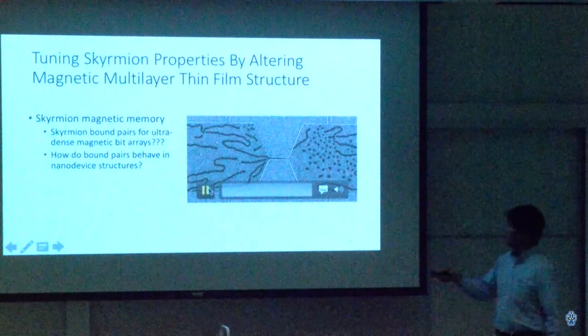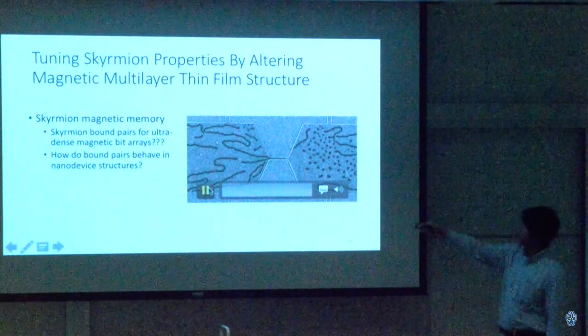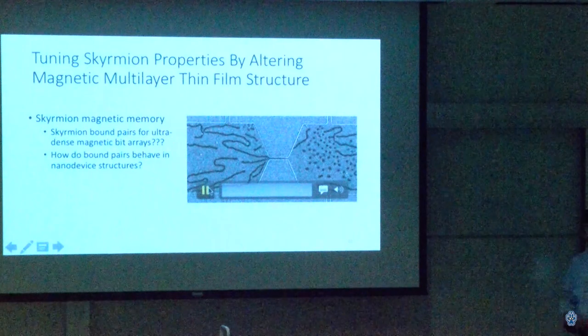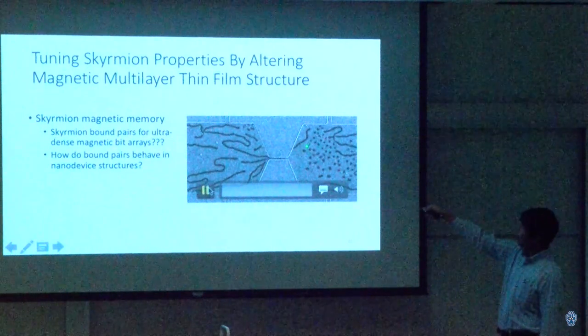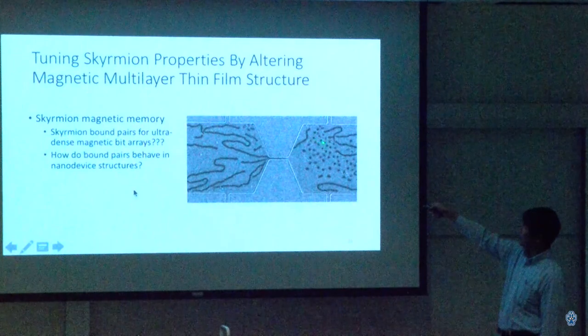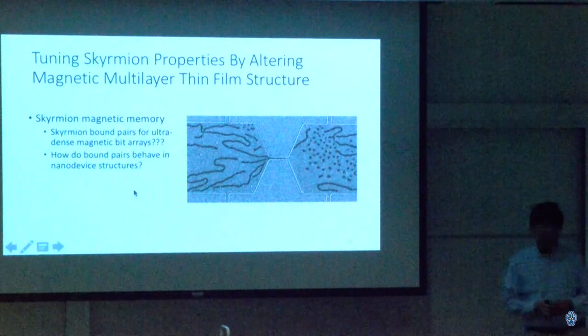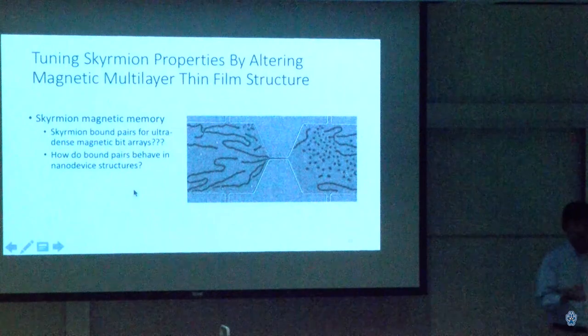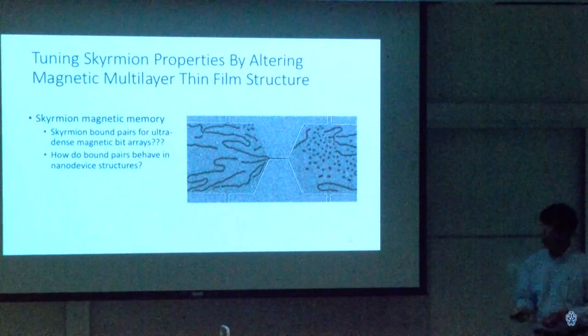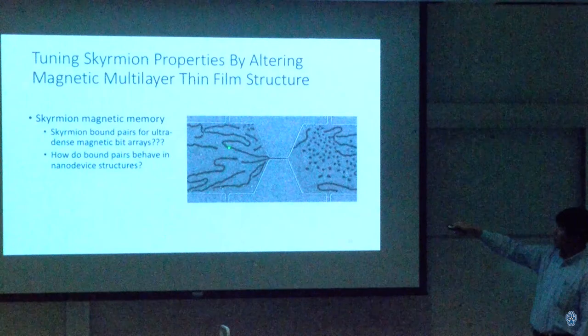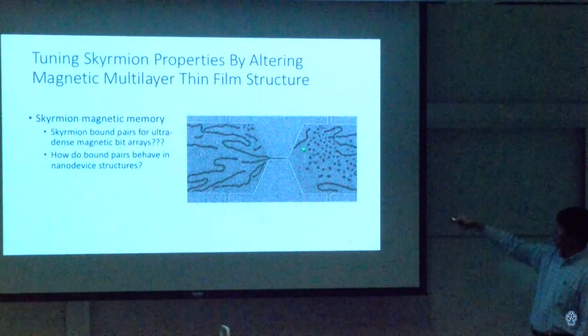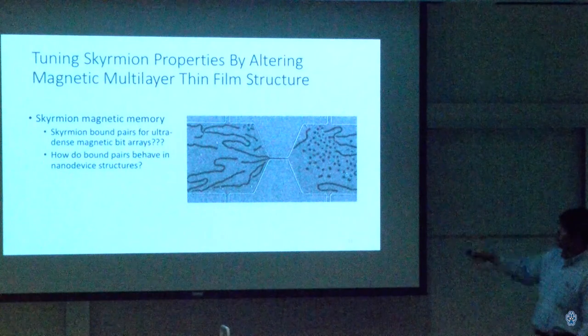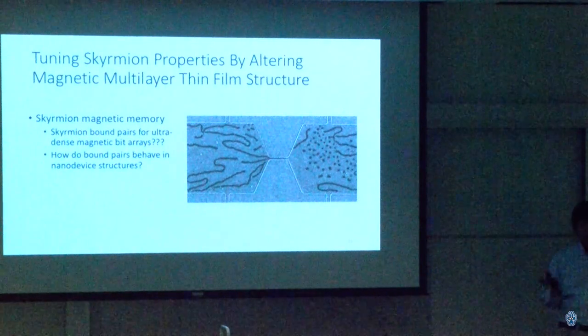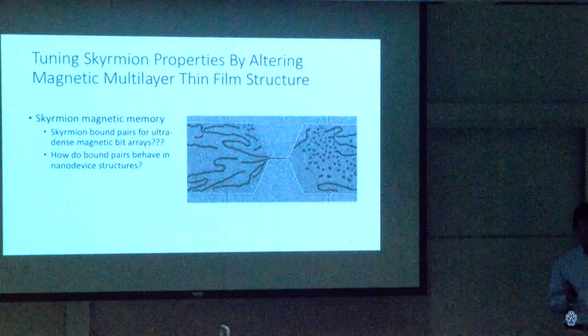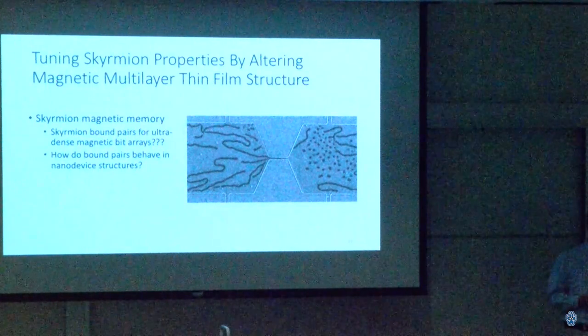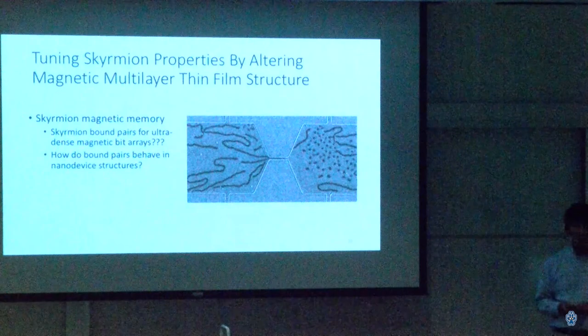Well, what you would have seen are these long magnetic domains, these worm-like domains moving from left to right. And when they do, they break up into these small skyrmion-like magnetic textures. So whereas we just applied a magnetic field to cause skyrmions to form in a thin film, others can force magnetic domains to break apart and form skyrmions in that fashion. The idea is that if you have multiple ways of creating skyrmions, you have multiple ways of creating skyrmion-based devices. And if you can create skyrmions easily, you can easily